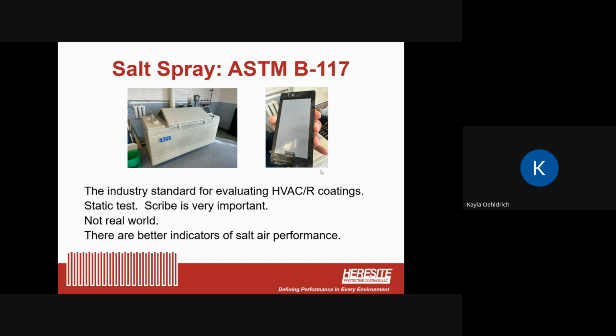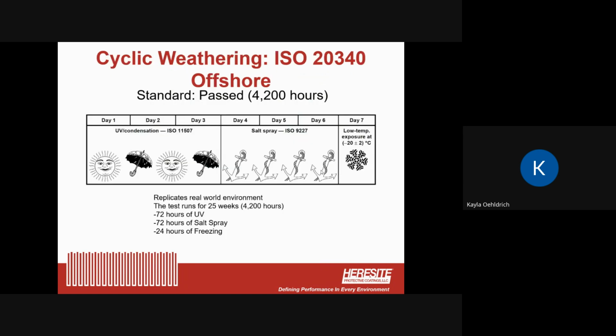While everybody uses this test, and we do too, to play what I call the salt spray game, we don't think it's the best indicator of salt air performance. We don't believe it's real world. There's no atmosphere that's the same all the time, that's static. So we really think that there's a couple of better tests that are done to predict performance. And the most popular one that we really talk about is the cyclical weathering test. So this test replicates the change in environments that a coating goes through and really is more realistic.